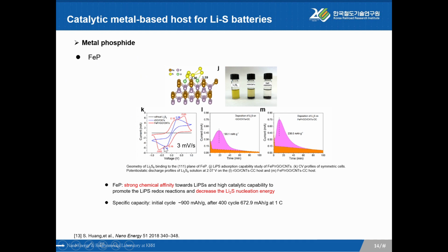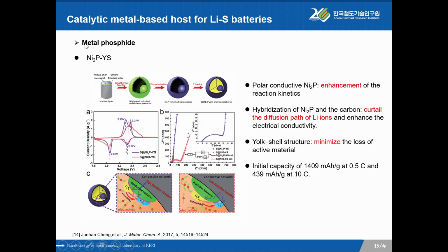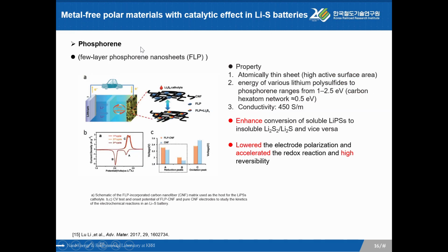From here we can see also the similar performance, the positive shift and the negative shift. And from here we can see lithium sulfide nucleation energy is lower. This is another kind of metal phosphide. This is a metal-free catalyst, phosphorene. From this peak we can see it is very stable. Also, there are 2 peaks. It means the reversibility is high. Also, it can enhance conversion of lithium polysulfide to lithium sulfide.